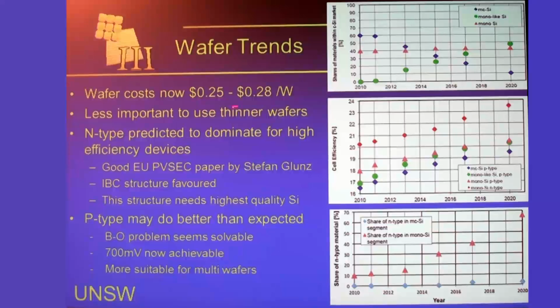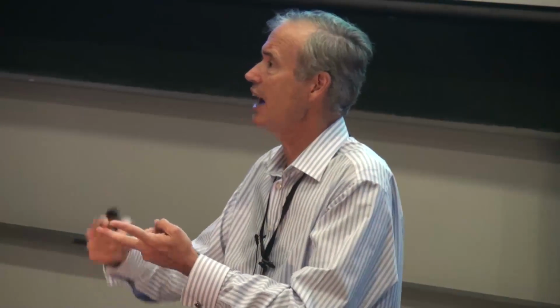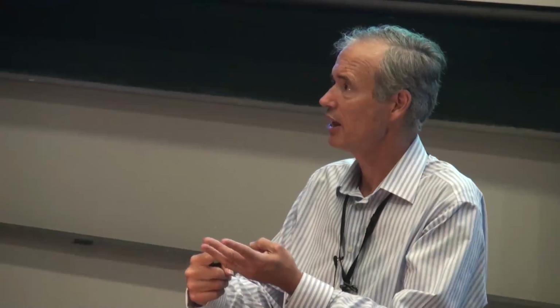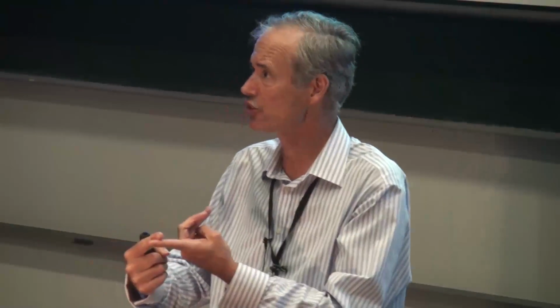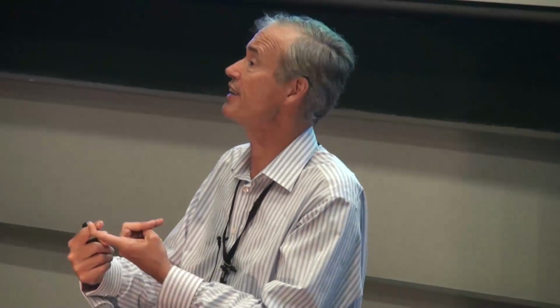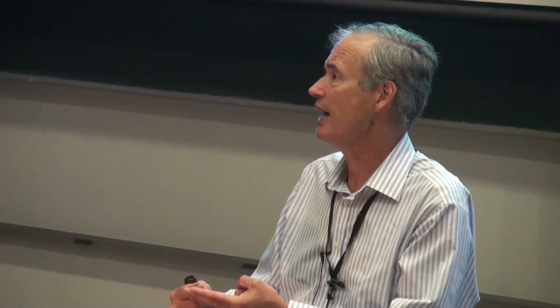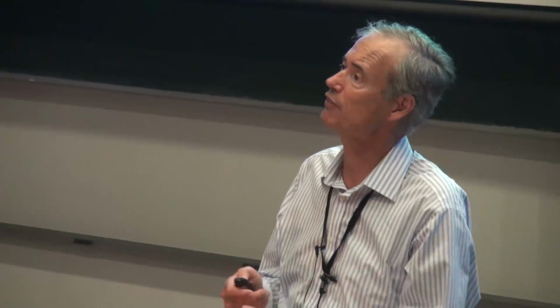quality? Well, these wafer costs have been driven down. The main contributors are the actual silicon purification costs, which is a big component. There is the formation of the ingot, and then there is the wafering. They're the three dominant costs, and it was always the silicon purification that completely dominated those three costs. But the silicon purification costs have been brought down quite drastically in recent years through economies of scale and also improved technology. And also the wafering, we've got new wafering technology, diamond wire sawing, and even before that, wire sawing, replacing the diamond saws. So we're seeing a lot of improvements in technology, we're seeing a lot of economies of scale. And even the casting process is now being able to be done a lot more effectively and at lower cost.